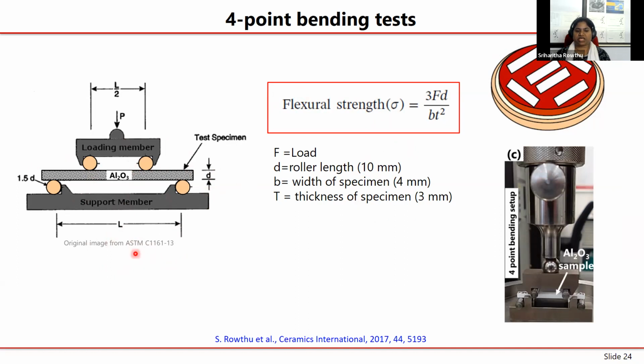It's actually as per the ASTM standard. So the flexure strength is given by this formula, 3 times F, the load that is applied. In this diagram, it's actually given as P, either F or P here. And D is the roller length. Okay. And then B is the width of the specimen. If this is your width, then T, thickness, will be into the plane of the screen, the thickness of the specimen. So these values are as per the ASTM standards.